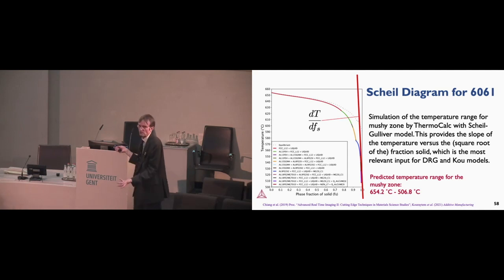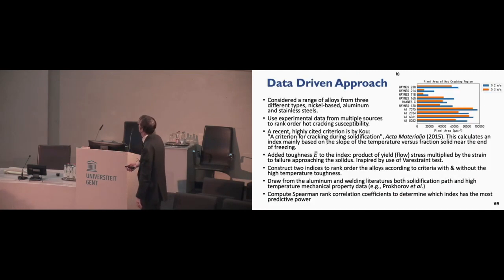And so we thought, well, maybe it's possible to take all this information that we can gather and do rankings on this. And so we took a data-driven approach. We gathered data for various nickel alloys, various aluminum alloys, and some variations in these, but basically to make some progress here, we started calculating Spearman rank correlation coefficients. In what order do these different alloys have good to bad hot cracking tendency? And what we found was that we didn't do that well with the Scheil approach, but if we added a hot toughness, then things got a lot better, interestingly enough.